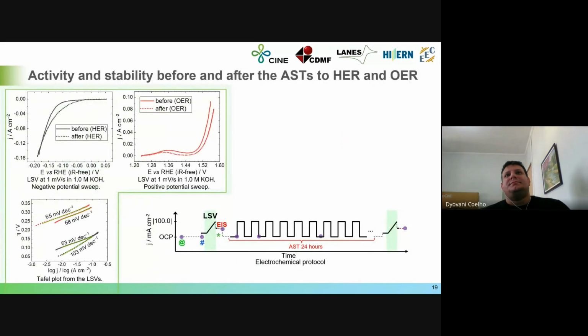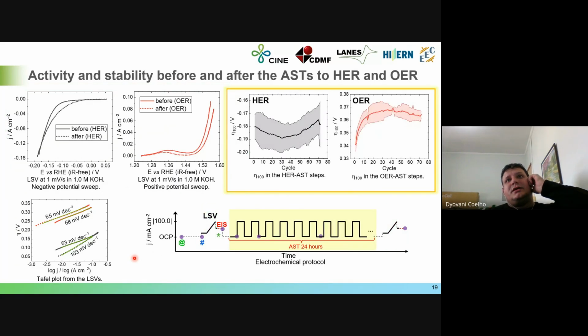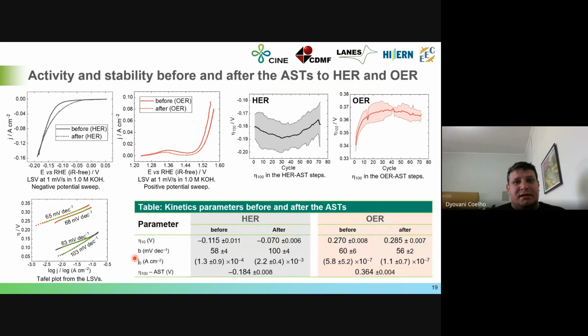So let's see what is happening. Here is showing for you the catalyst activity before and after the accelerated stress test. And here I show for you the catalyst overpotential during the accelerated stress test at 100 milliampere per centimeter squared. The first thing that we can see is that for hydrogen evolution reaction, there is a decrease in the overpotential to reach 10 milliamperes per centimeter squared.